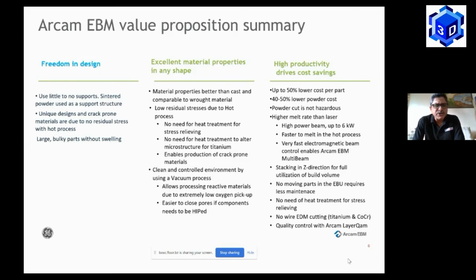So the mechanical properties, if you compare EBM produced components, are in most cases proven to be better than cast and comparable to forged and wrought materials. We also have very little oxidization because of the high vacuum environment inside the build chamber, which enables us to remove impurities from the chamber and the environment. That removes the significant problems that occur when the melting process happens, thereby offering consistency on each build. And it also helps us to build many reactive materials like titanium and other materials.